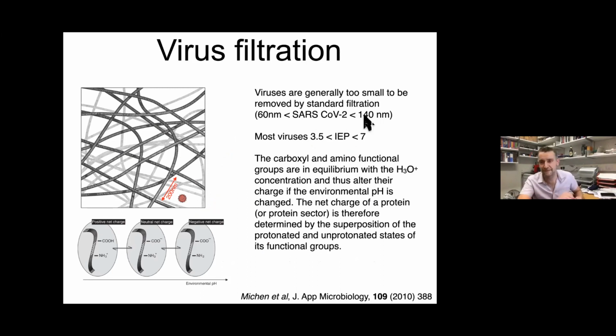But the thing is that because it's a particle, as far as we're concerned, it has a zeta potential. And the other thing about viruses is they're always aerosolised, right? If they're not aerosolised, they're not actually effective. They're not going to hurt you. So that means they're always in water, so you can exploit the zeta potential. Most viruses have isoelectric points somewhere between 3.5 and 7. This is just where the zeta potential curve crosses 0. So that means they're mostly negatively charged, okay?